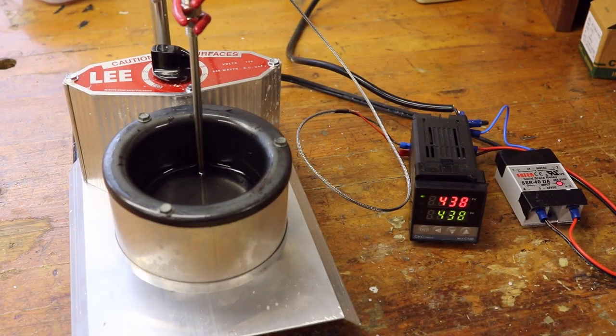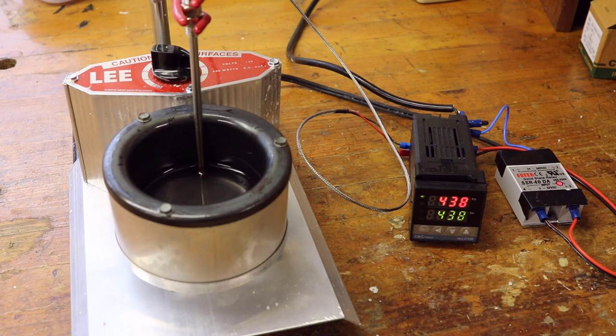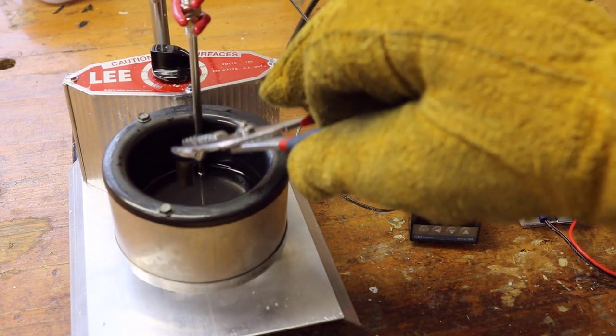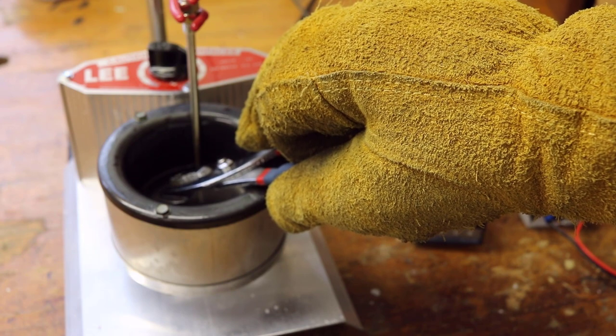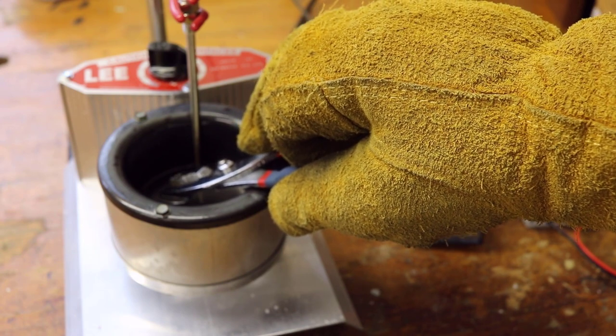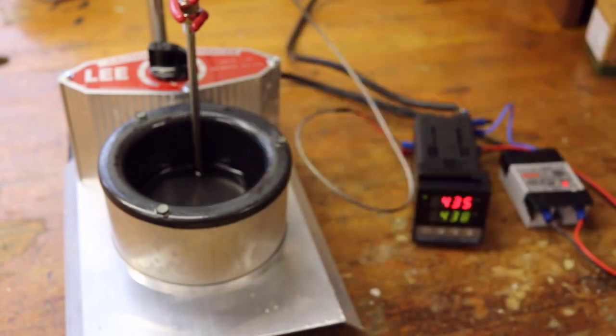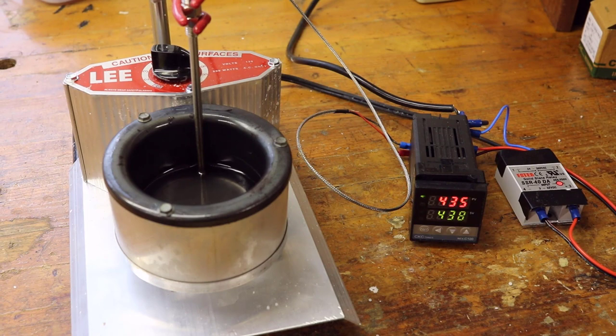I took its twin brother, and after every six or so, six or seven cranks, I annealed it. And I never could get it to fail, so it was clearly annealed.